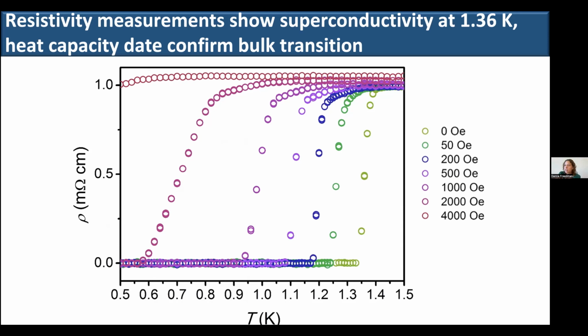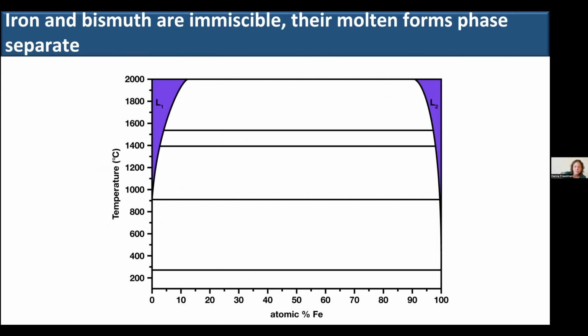I don't have it in these slides, but heat capacity data are also indicative of a bulk transition in this material. Okay, so we've shown that we can use diamond anvil cells to scan phase space and figure out where we can find new phases, and then we can replicate those phases in a multi-anvil press and acquire properties measurements.